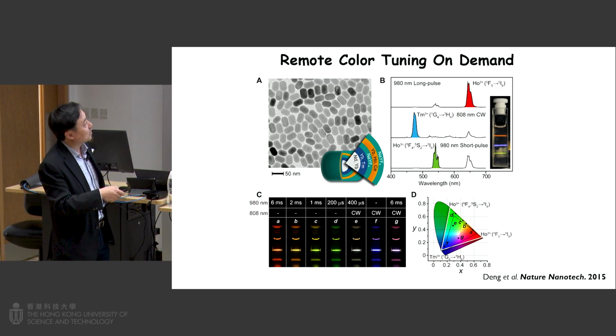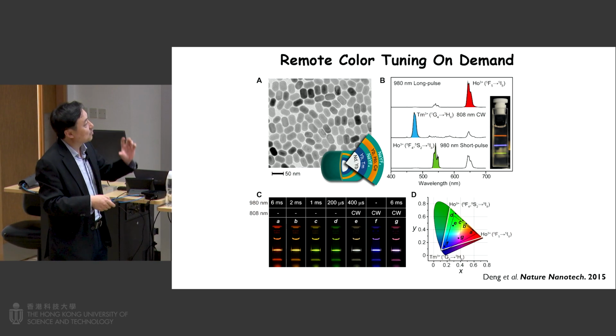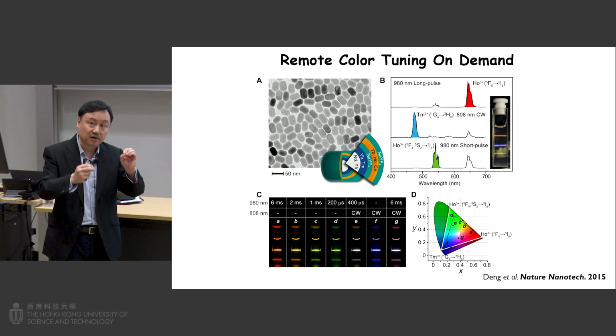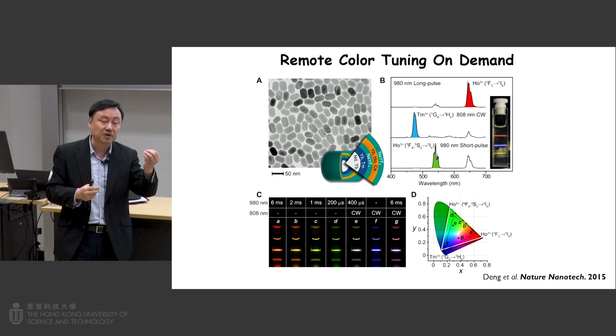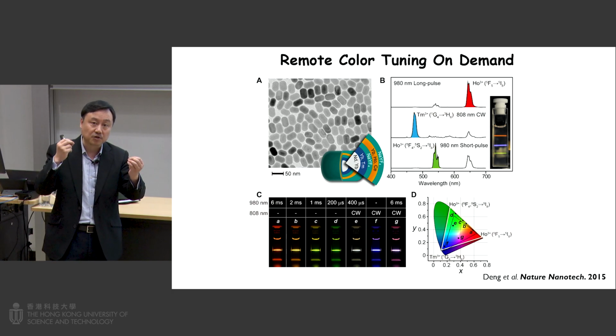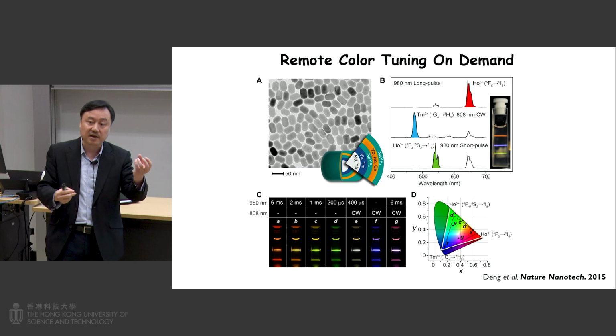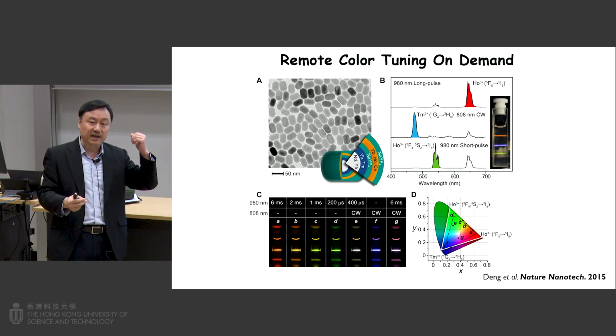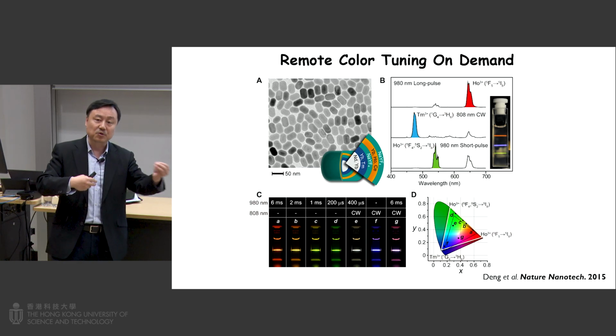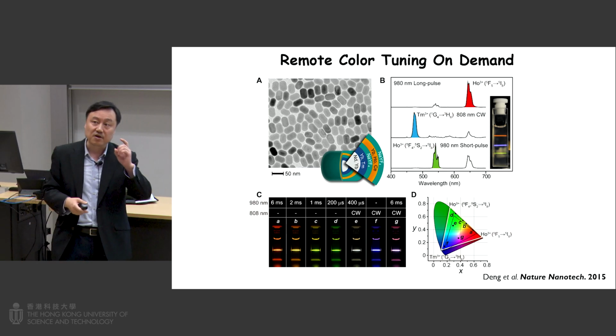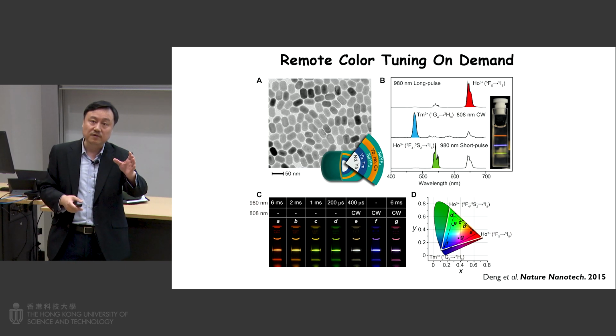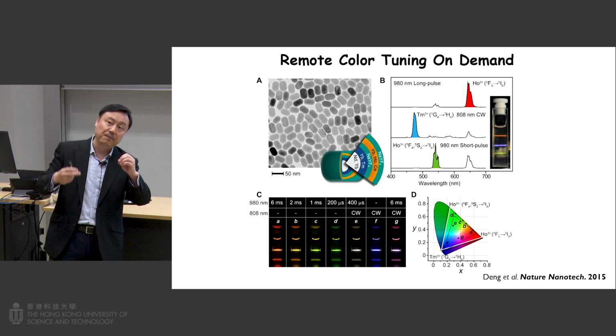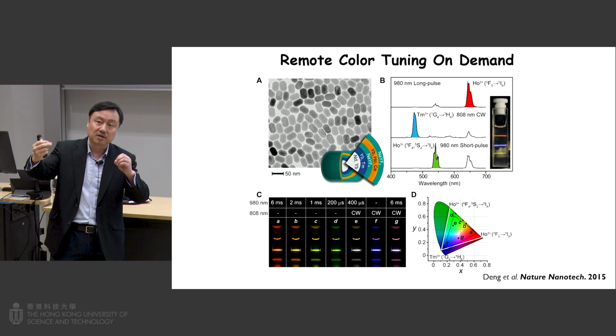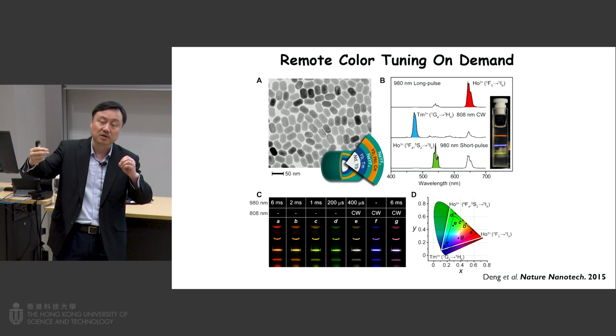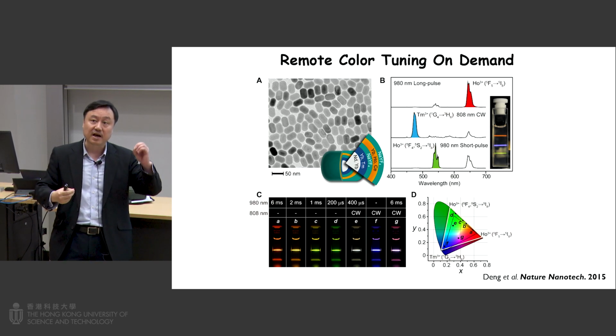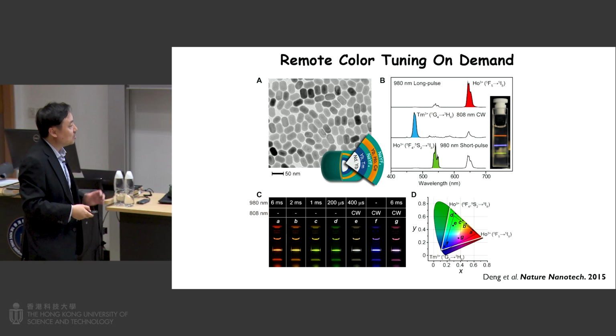For this work, what we have achieved is that we want to tune the particle luminescence without changing the particle composition. This is very challenging. For quantum dots, if you want to tune the color, typically you have to change the particle size. But that means you go back to the lab, synthesize the materials, and keep going back and forth. So the question is, can you make materials with a fixed composition, but upon changing the external stimulation, for example, the pulse duration or pulse frequency, change the color? That's the fundamental question we have. It turns out that we can do that.